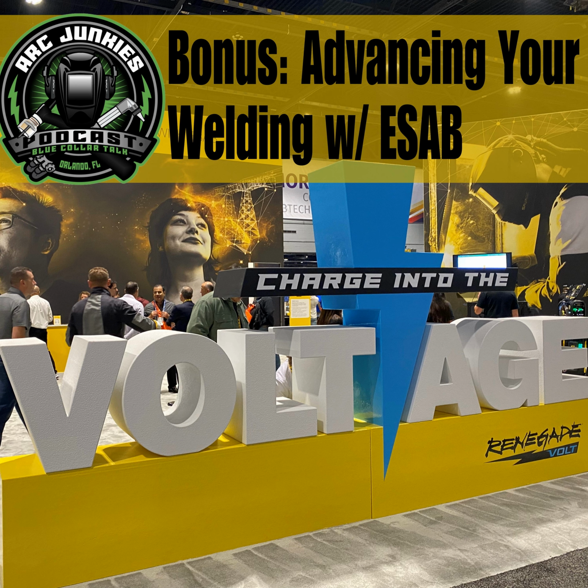He comes back, I want a little bit more. Well, we can go to AC. Let's go to AC. He says, I want a little bit more. Okay, let's vary the waveform. Okay, I want a little bit more. How about we go to ICE? Great, I want a little bit more. I want to parallel two power sources because I can give this. So we went from a single power source, 700 or 800 amps, to two parallel power sources at over 1,400 amps. We go from 18 pounds an hour to over 100 pounds an hour deposition rate.